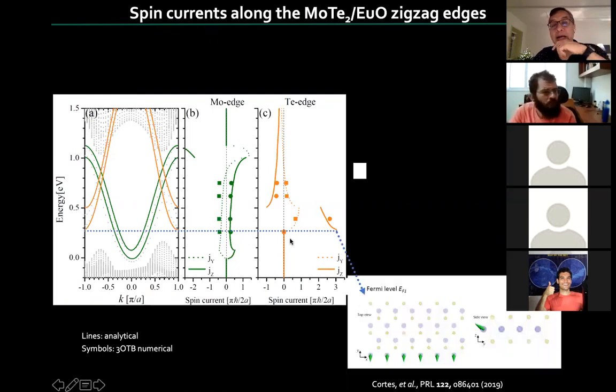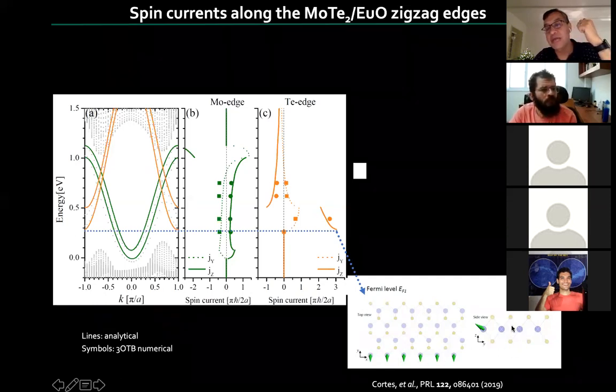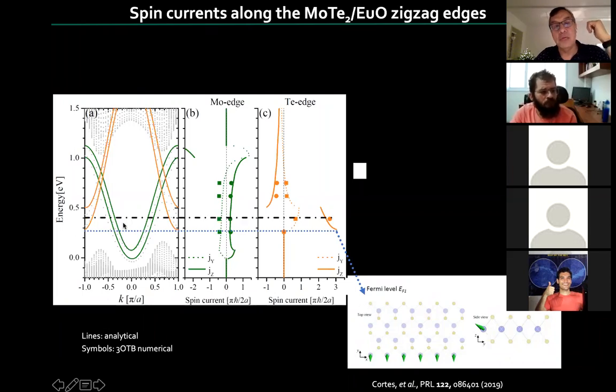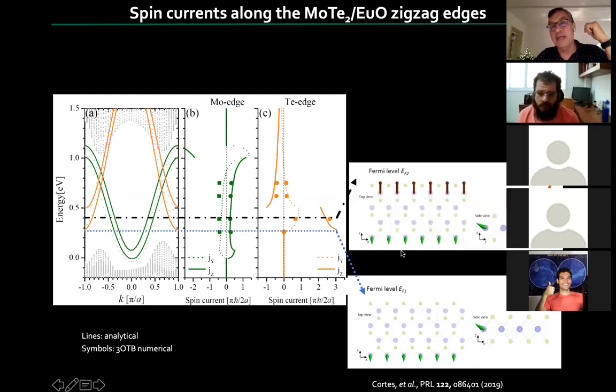So if I were to make a cartoon of this, this will be the ribbon. You can see that the tellurium edge has no current because this is zero, but the moly edge has a current in some direction. Here is a top view, this is a side view, that depends on the combination of these two currents. All right. Now imagine that I change the Fermi level, increasing it. Now I still have the two channels on the moly edge. Now they're conducting roughly the same, but now I've started to conduct on the tellurium edge. And in fact, because it is just the beginning, it's only one branch and it conducts rather well. So the cartoon of that shows again